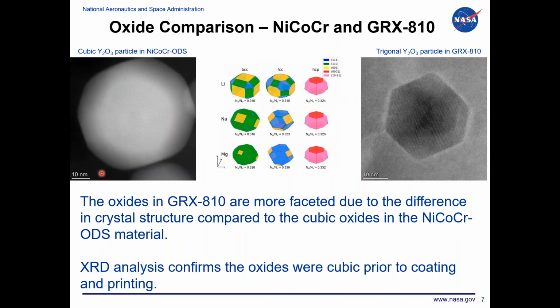Now, something that's been very interesting that we've recently found, and so we're digging real deep now into the characterization here of ODS alloys. But when we start coating these powders, we always start with cubic yttria. So that's the crystal structure of the yttrium oxide. It's stable. Crystal structure is cubic. It's almost how you would assume yttria will be. And in fact, when we produced nickel cobalt chrome ODS and 3D printed it, when you look at it in the microscope at very high resolutions, sure enough, it's cubic. And you actually can see the facets of the single crystal cubic structure here.